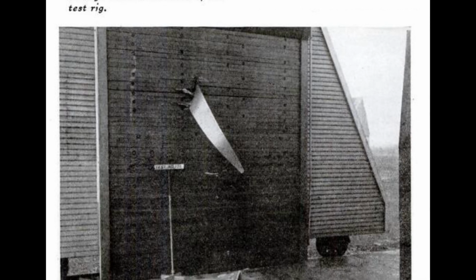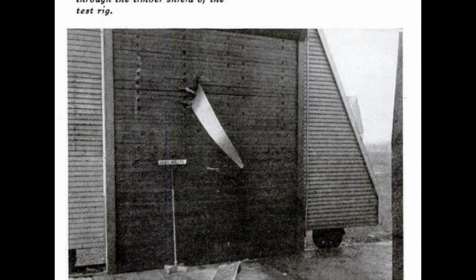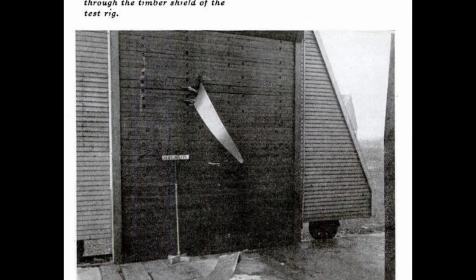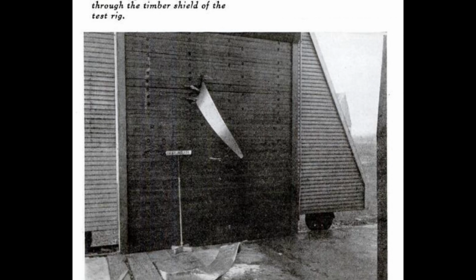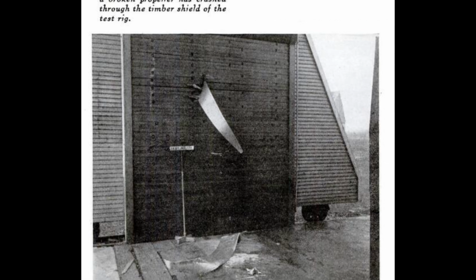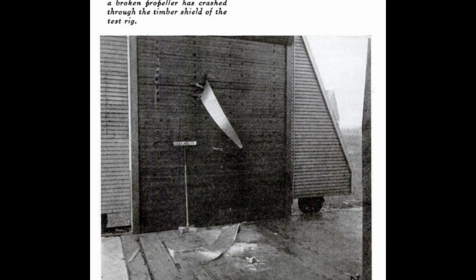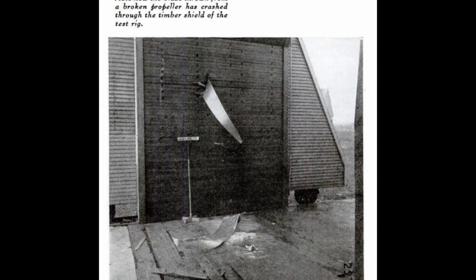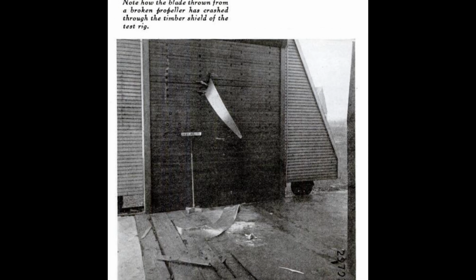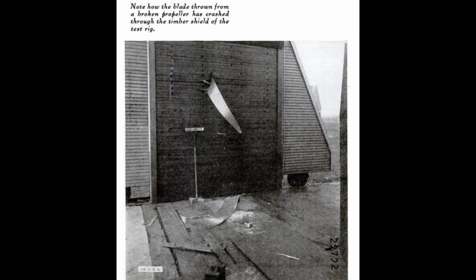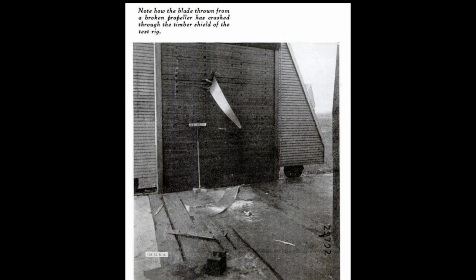Hence, fatigue failure is frequently noticeable in such thin metal objects as automobile fenders, so often marked with spreading cracks. Wood is immune to fatigue failure, so propellers did not break from this cause until they were made of metal. Duralumin is particularly susceptible to fatigue failure, and the barely noticeable fluttering of the rotating blades is apt to cause tiny cracks after a few million revolutions, and in the course of additional millions of revolutions, such cracks develop into actual breaks.